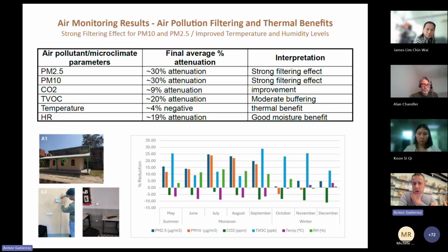And there is a strong attenuation, especially for PM particles, around 30% attenuation compared with external conditions, and 20% attenuation compared with the control room, which suggests that the material is having a filtering effect on air quality, which we still don't know why is happening. We have brought a couple of blocks from the building back to analyze in the laboratory. The hypothesis is that the surface of the material is trapping some of the PM2.5 and PM10 into the surface itself. So as we were mentioning before, the material has the capacity to breathe.